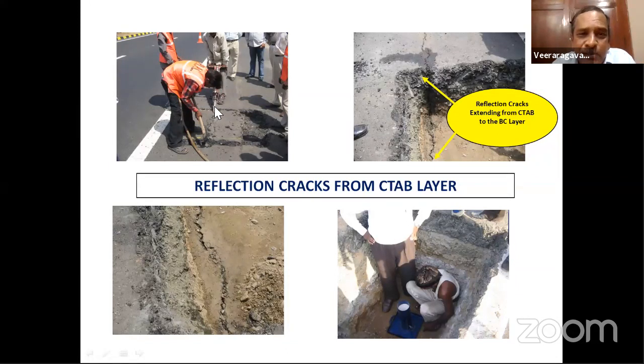This is a crack that I observed on the Ahmedabad Vadodara Expressway all along the shoulders. I was surprised to see a longitudinal crack all along the shoulders, so I tried to find out what went wrong. I excavated, took pits, and went up to the subgrade level and subbase level. I could find cracks on this, which was a cement treated base. They had widened the embankment and did not do bench cutting. When they widened it, because of settlement of the subgrade and embankment, the cement treated layer cracked. From the cement treated base, the crack has propagated up through the granular subbase, the wet mix macadam, the DBM and BC. You can find the cracks there. So these are some points on which we need to take precautionary measures before we design the road.